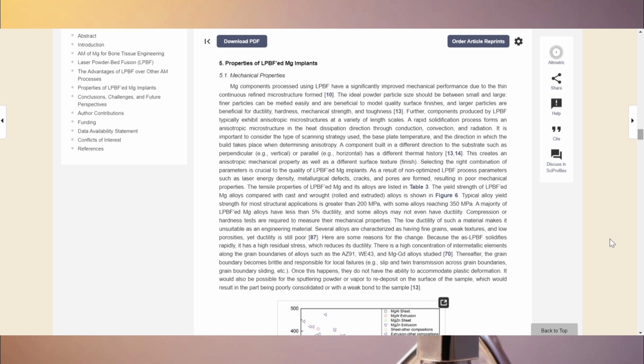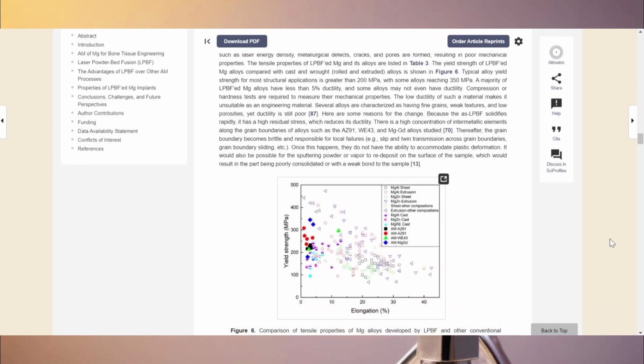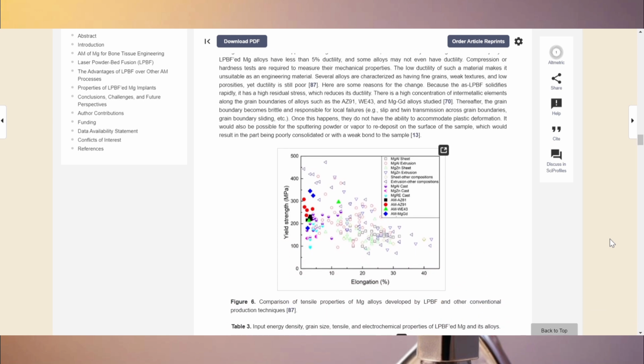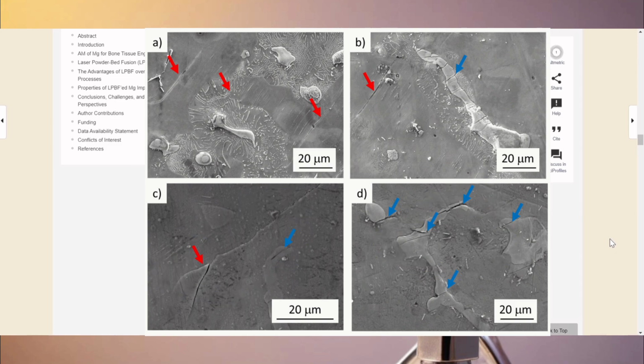Since LPBF involves rapid cooling through conduction, convection, and radiation, the microstructure develops differently along the building direction. An implant built vertically, perpendicular to the base plate, experiences a different thermal history compared to one built horizontally, parallel to the base. To ensure optimal results, every aspect of the printing process must be fine-tuned. Factors such as scanning strategy, base plate temperature, and build direction all play a role in determining the final implant properties. If the LPBF parameters, particularly laser energy density, are not precisely controlled, defects like cracks, pores, and metallurgical inconsistencies can weaken the implant.